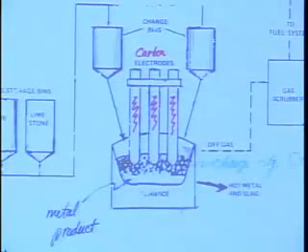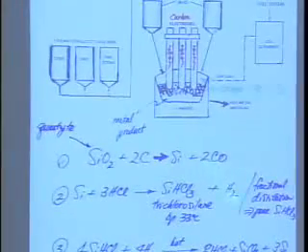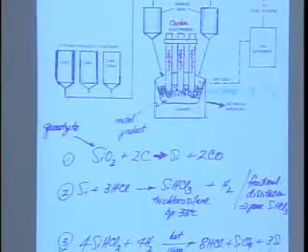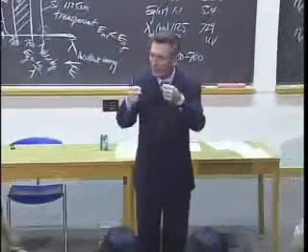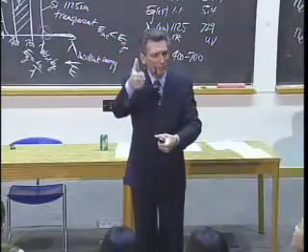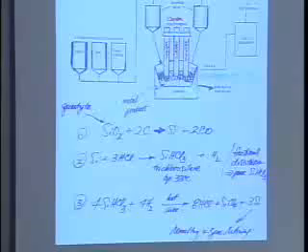The carbon reduces the silica to elemental silicon and generates carbon monoxide. And the carbon comes from the electrodes themselves. So you consume the electrodes. So the electrodes are constantly being fed like giant drafting pencils into the charge while they're passing current. And now we make silicon.